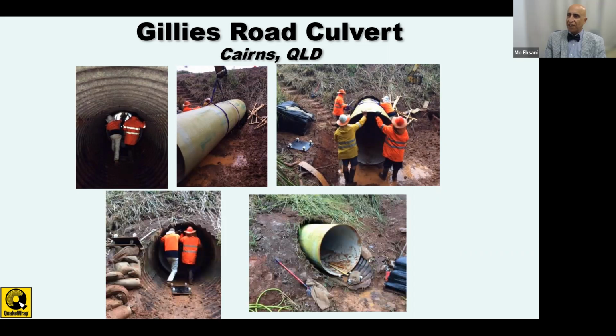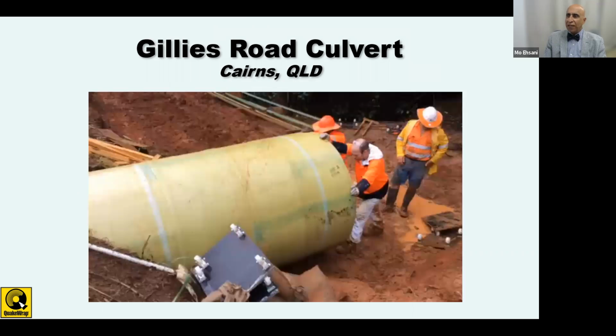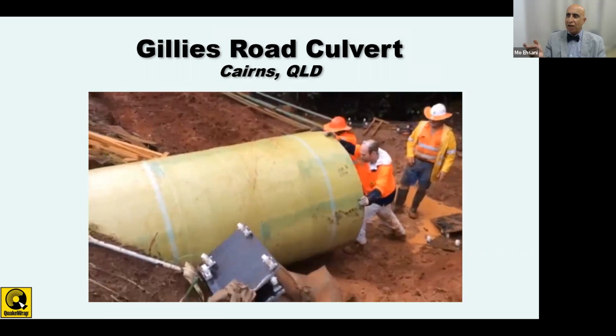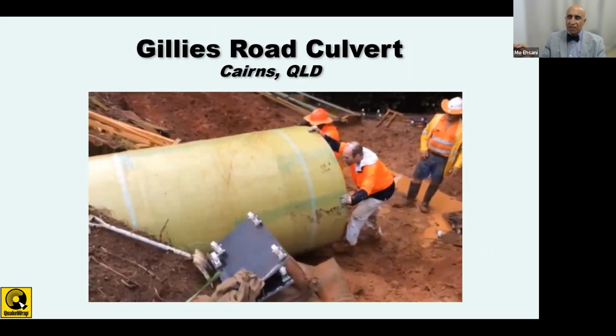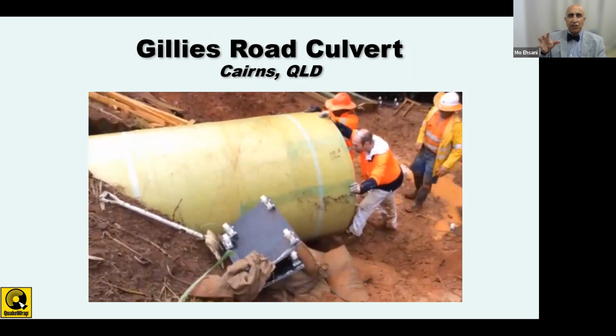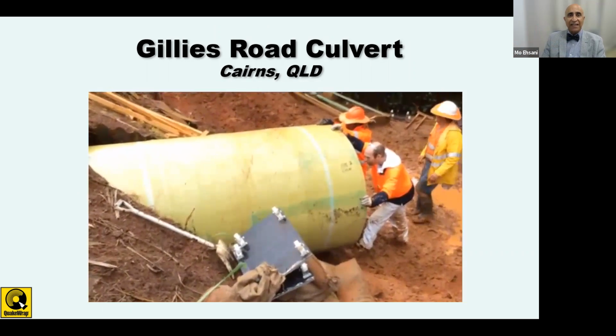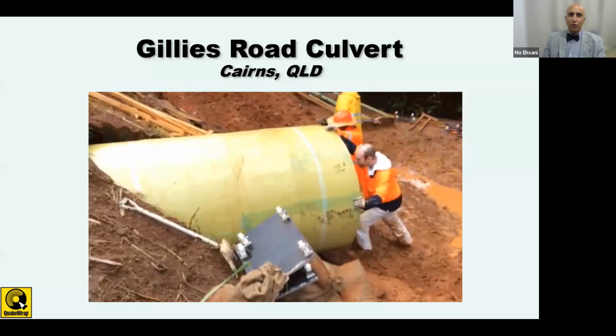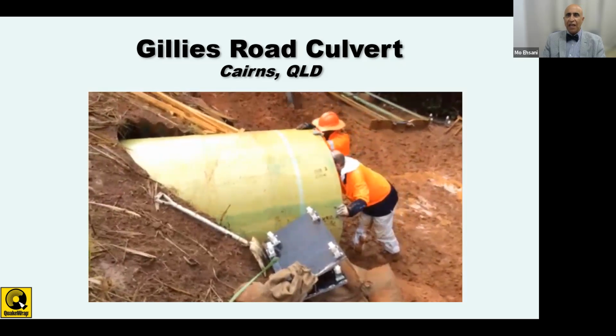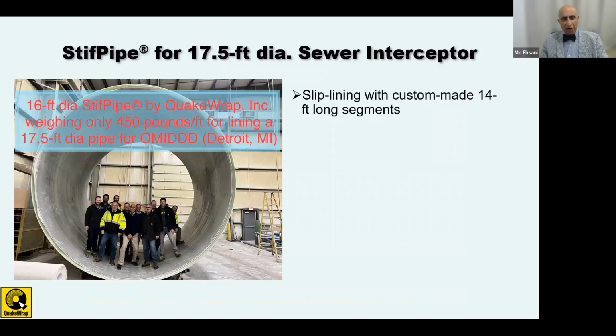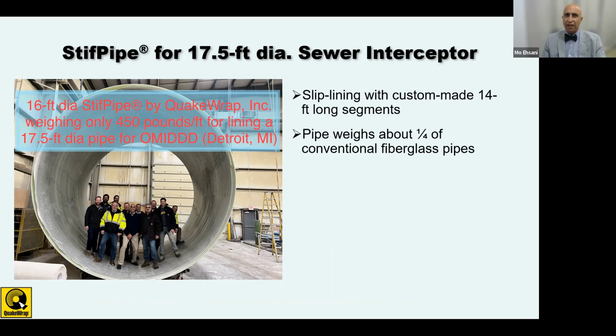And so this is getting close to the finished pipe. But look at how light this pipe is, that these 2 guys are pushing it by hand with no equipment, just sitting on a couple of those casters, pushing it into the pipe. The fact that this is such a light pipe makes a big difference for many of these projects. We are now doing a major project in Detroit that, as far as we know, is the largest such pipe made in the US today. This tunnel is 17.5-foot diameter. It's a sewer interceptor that is deteriorated.